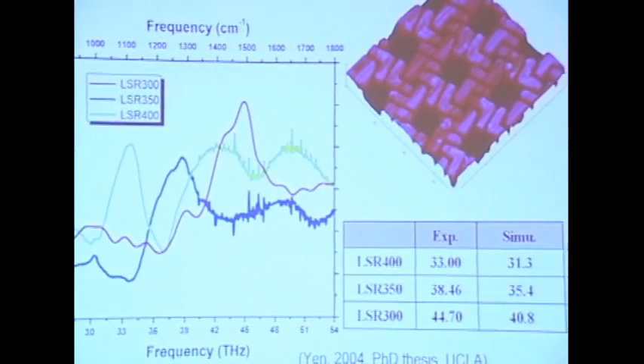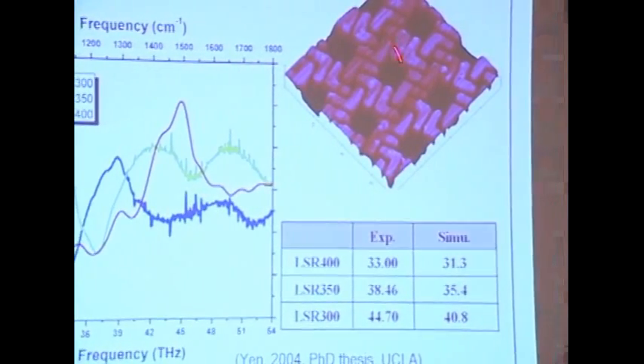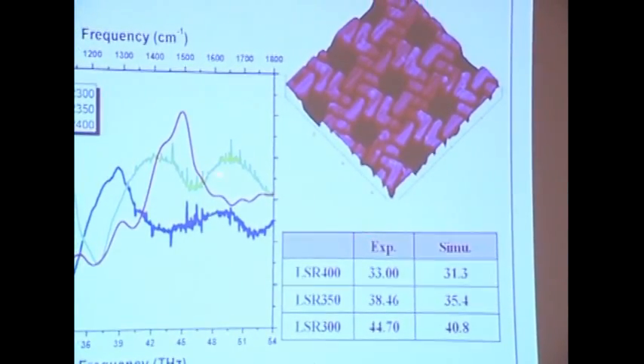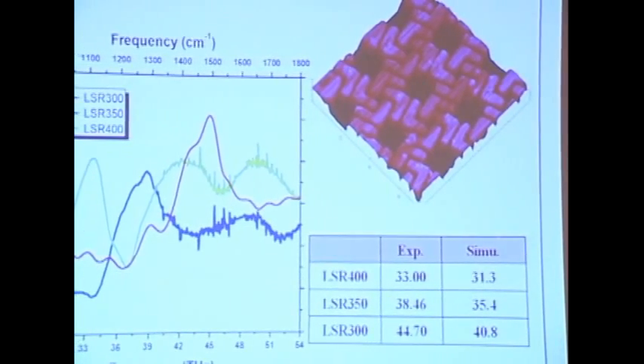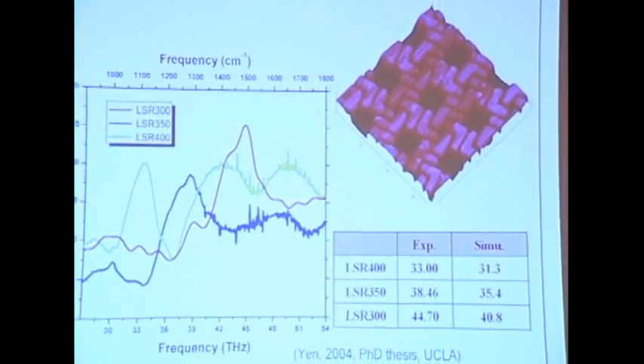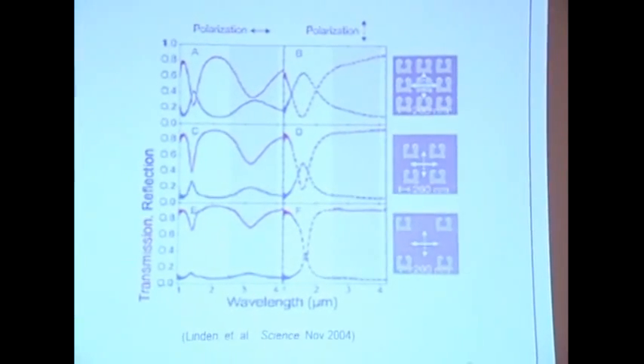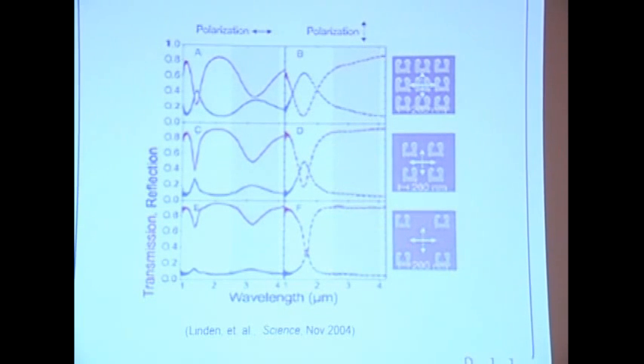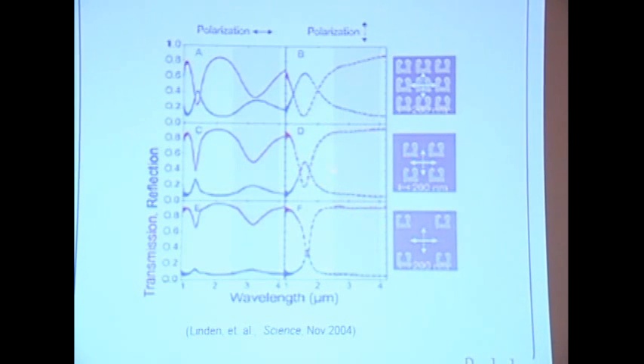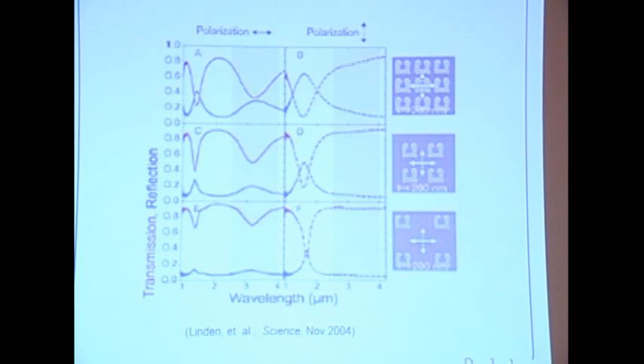In this case, we are also very interested in the atom-atom interaction as well. That is also very interesting to look into through a near-field interaction. And also, a German group at the same time reported even higher magnetic material at about 3 micron or 100 terahertz. This is about a span of less than a year. So it was a really hot kind of race.